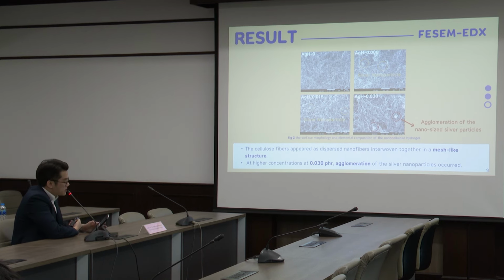The FESEM image we observe at a magnification of 20,000 reveals that in each concentration, the cellulose fibers appear as dispersed nanofibers interwoven together like a mesh, as you can see in these four pictures. In addition, there were silver nanoparticles distributed throughout the sample, as you can see in Ag 0.008 to Ag 0.030. However, we observe that at the high concentration, accumulation occurs, as you can see in the last cycle.